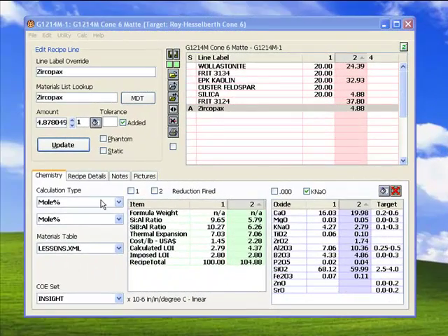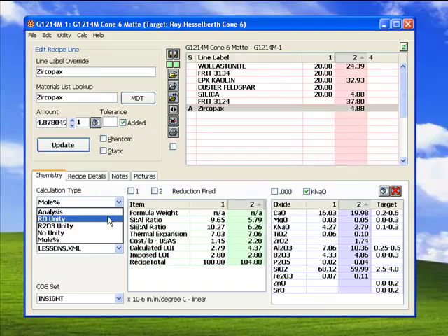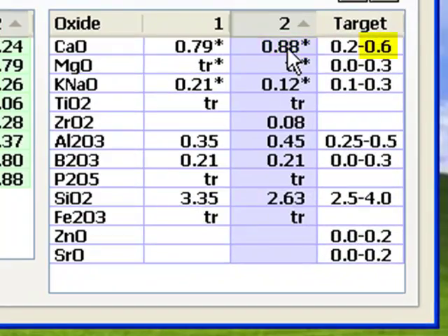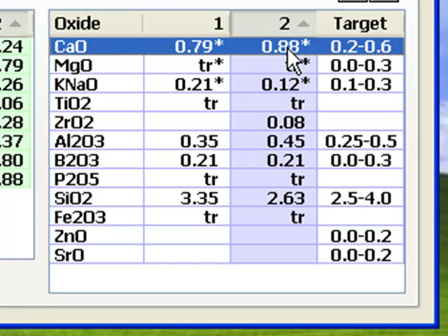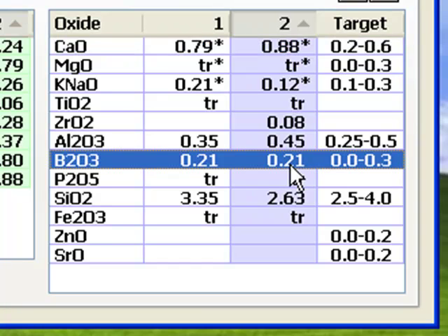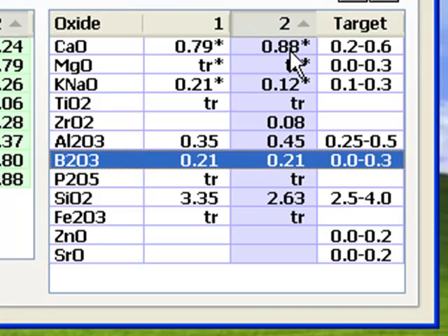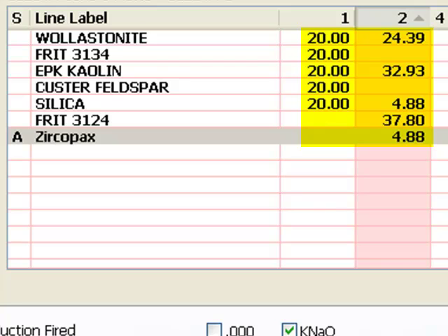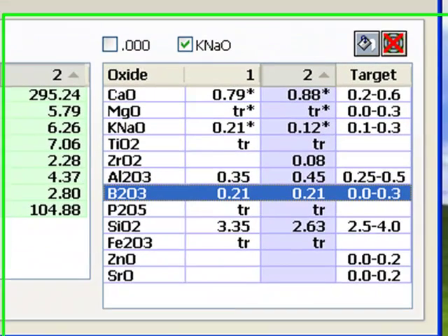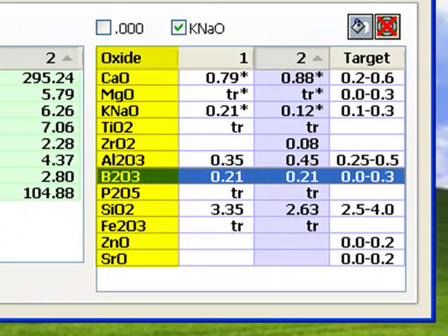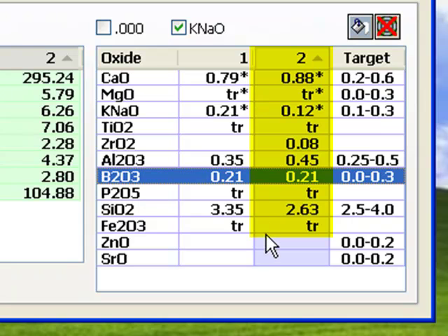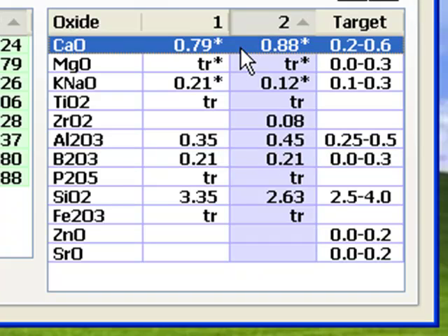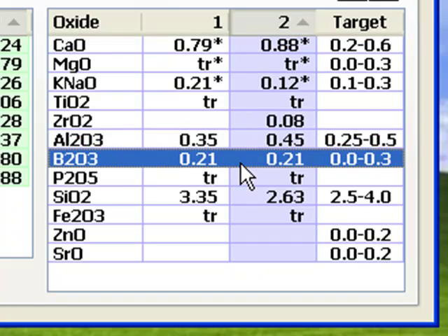You might have some questions. How can I get away with CaO that is higher than the limit? This is often acceptable if MgO is near zero and if there's plenty of B2O3 to melt things well. Remember also, chrome-tin colors require high CaO, and matte glazes work best with it as well. Also, since these recipes look so different now, you might think it is a stretch to say that the matte is an adjusted version of the glossy. But remember, we're working on the oxide level. This matte formula is an adjusted version of the other. High calcium glazes can have leaching problems, but we have high alumina and plenty of boron to help melt it. These are stabilizing influences.